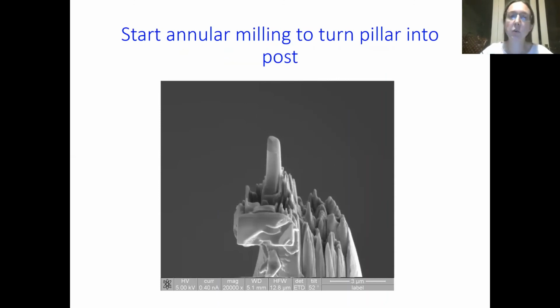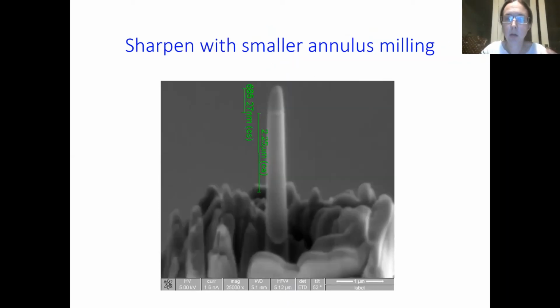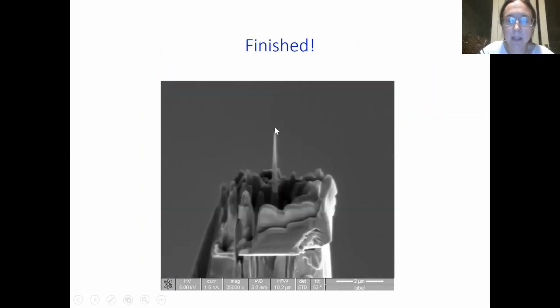And then we start to do what we call annular milling, which means like donut-shaped milling, milling away to get a thinner and thinner and thinner post. So here a sort of cylindrical post. And then we sharpen it, making our annular milling have a smaller and smaller and smaller inner radius until we have this very, very thin needle. So that's the finished atom probe specimen for one of our earliest gallium nitride atom probe experiments.